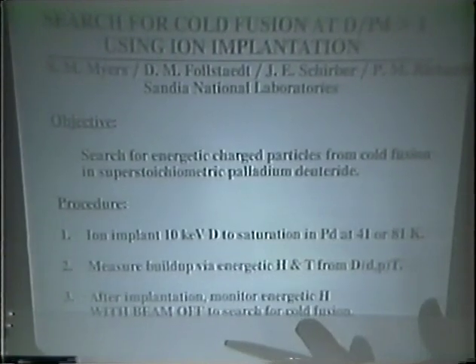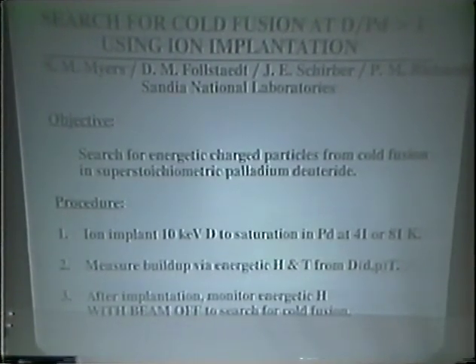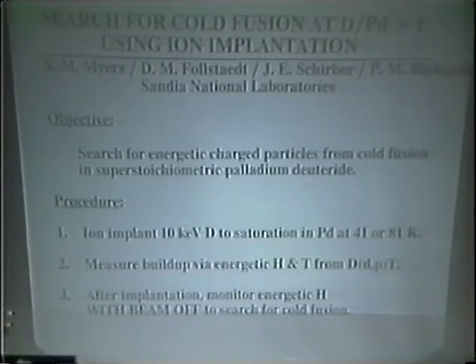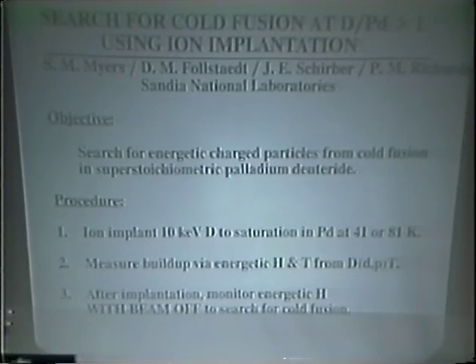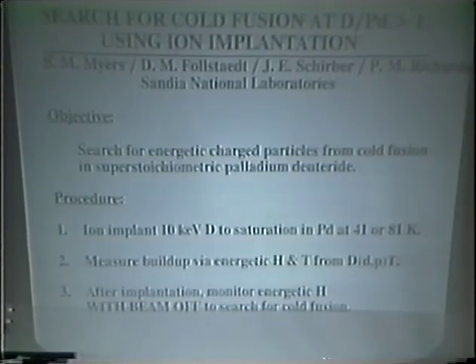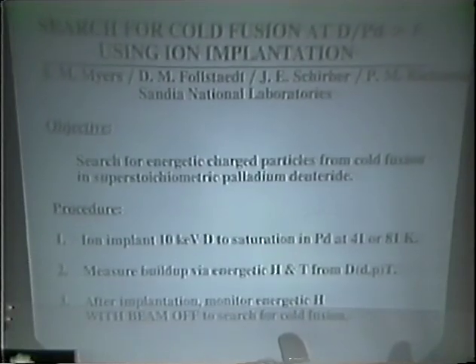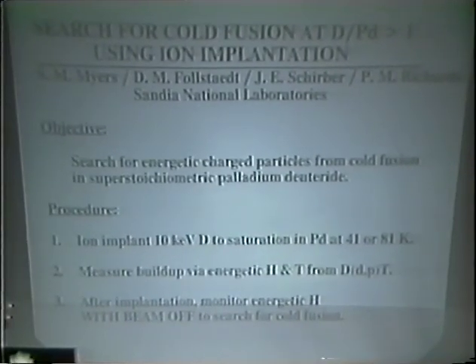So our experiment basically consisted of performing low temperature implantations to achieve these high stoichiometries, and then using a charged particle detector to look for the energetic particles from DD nuclear reactions. Of course, as has been apparent from this conference, when one uses high pressure gas phase charging or electrochemical charging, these higher atomic ratios, in particular atom ratios above 1, are not easily achieved as they are with the implantation.